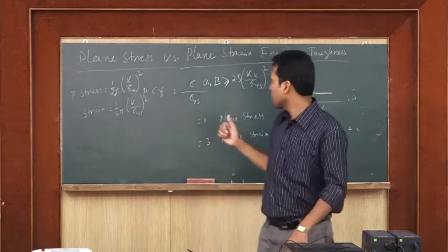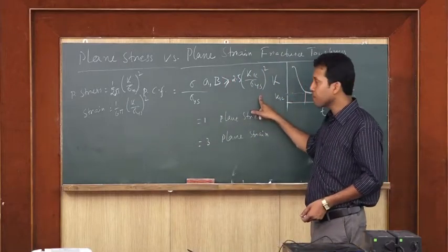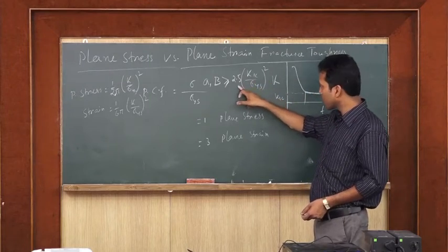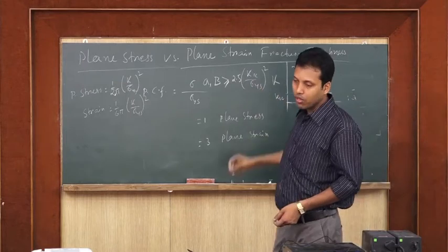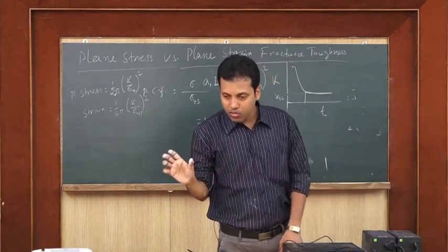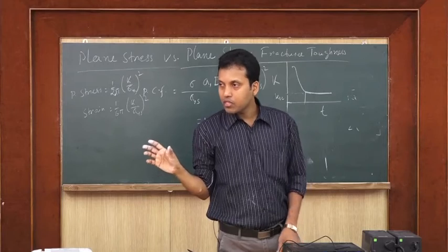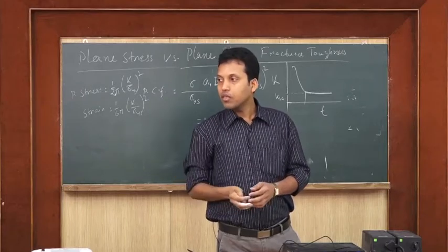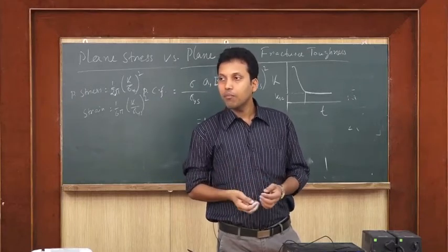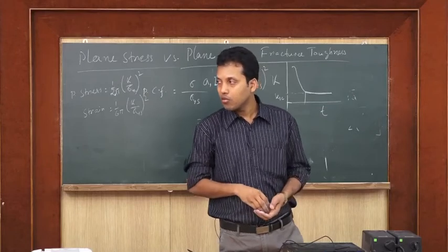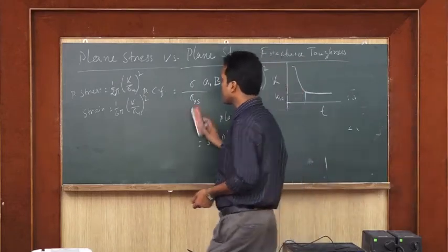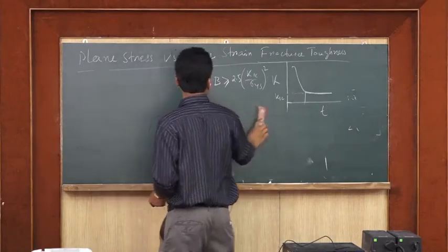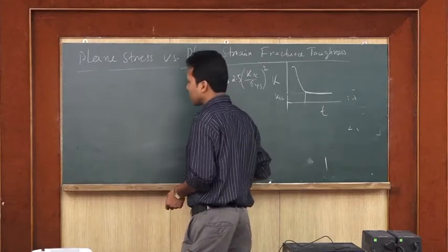So, that is the valid fracture toughness test specimen design, and here you can see that leaving aside the 2.5, the other term, (K1C by sigma ys) whole square, is related or similar to the plastic zone size, rp. So that means the specimen design, whatever we are making, is somehow related to the plastic zone size of a material. Okay. So specimen thickness is somehow related to the plastic zone size of the material. How it is related, that also we will see later.